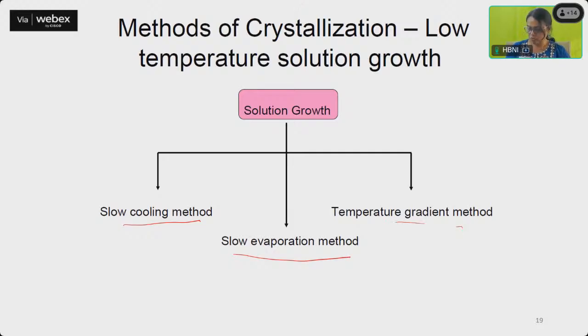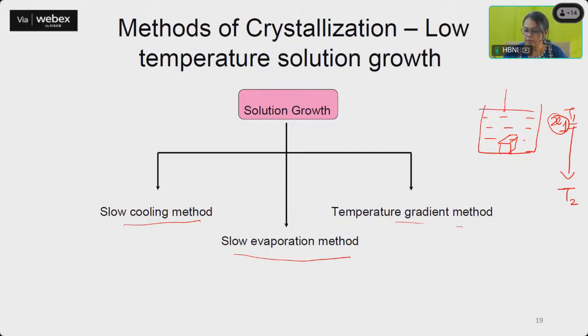The slow cooling method is nothing but, like I said, we have a bath and we dissolve some X1 amount at T1 temperature and slowly we bring it to T2 temperature, so that it is supersaturated at X1. So we will have some material growth in this. Or if you want nucleation, we can put a seed crystal, and the crystal growth starts on this seed crystal. So this is the cooling method. We are decreasing the temperature.